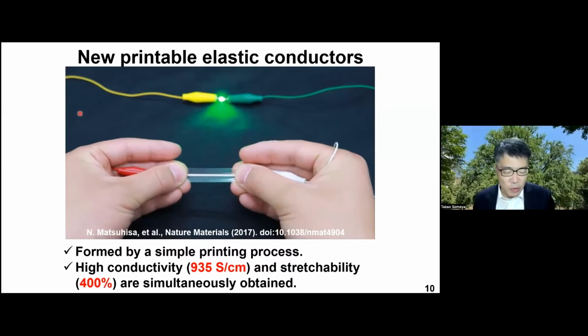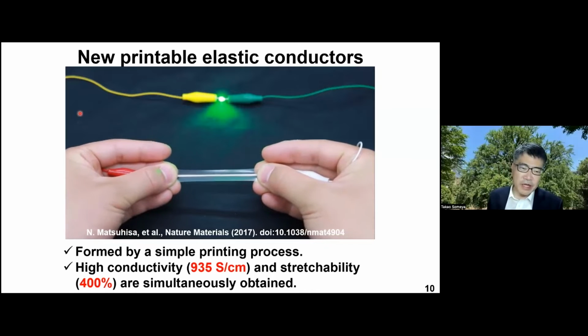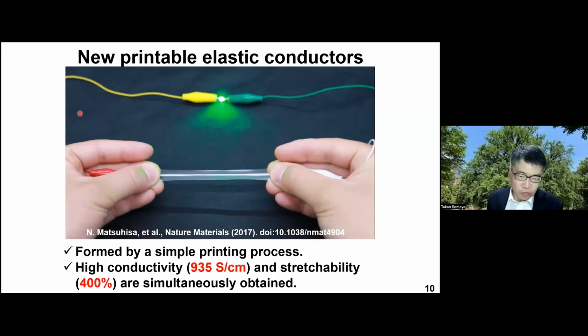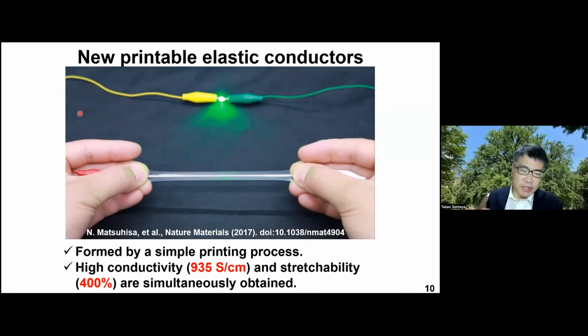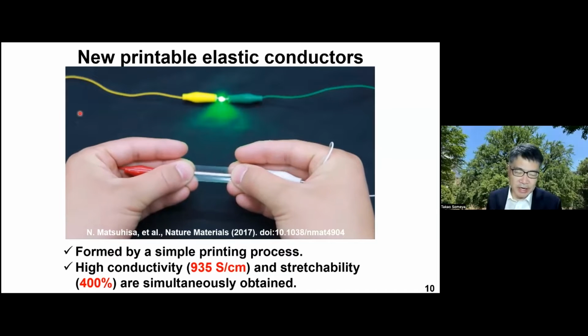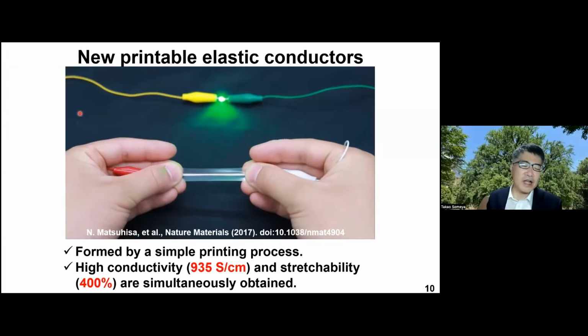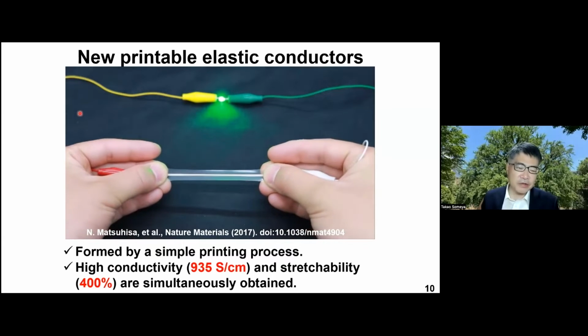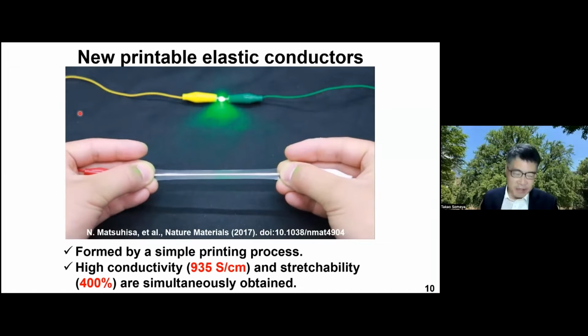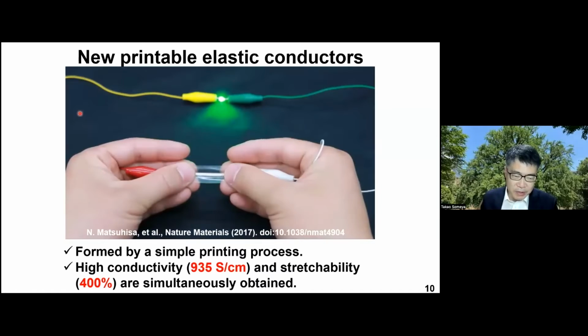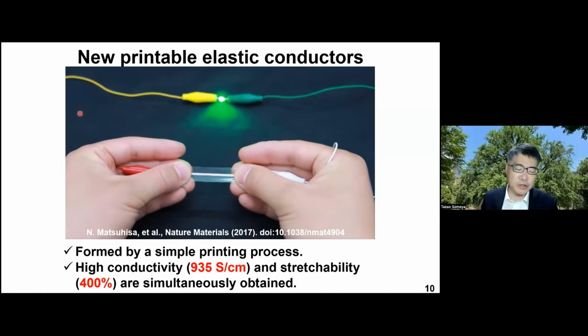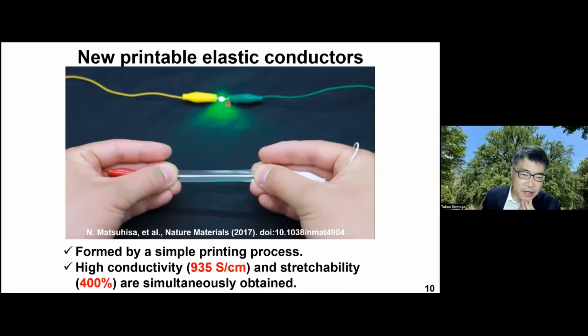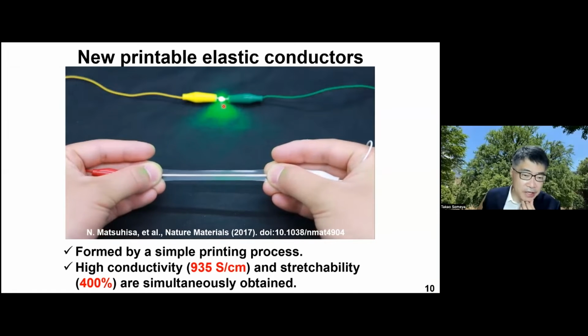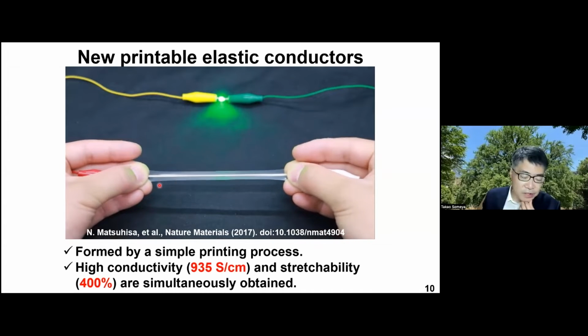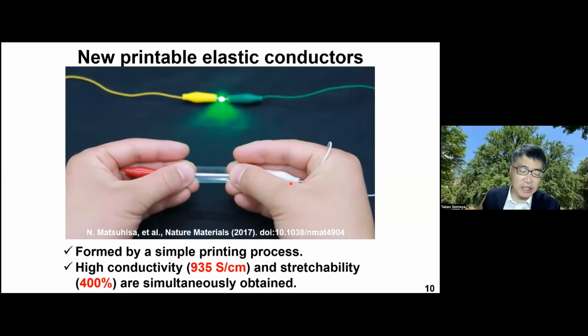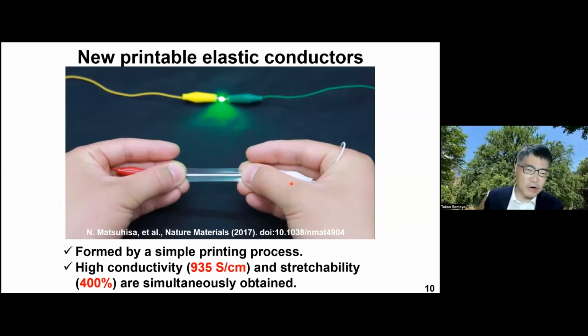To build the stretchable integrated circuit, the newly developed elastic conductors play a very important role. We can print the elastic conductors once onto the rubber substrate and anneal at 140 degrees Celsius. And then we can achieve high conductivity close to 1000 Siemens per centimeter and stretchability over 400% simultaneously. You may see the bright light emission from the LED, and the brightness doesn't change at all. This means that the change of resistivity is sufficiently low. This is quite a unique feature of our elastic conductors.